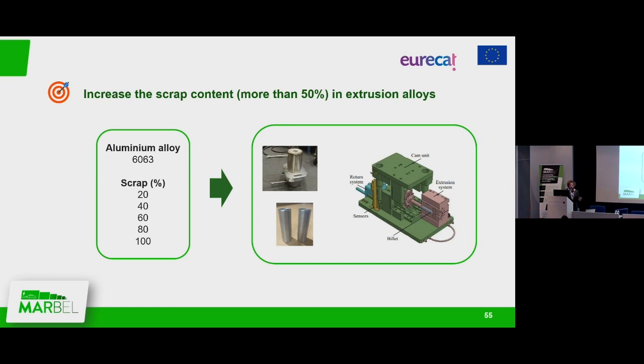Our scope was to increase the scrap content to more than 50% in extrusion alloys. As Elias told before, we used 6063 aluminum alloy, and we included 20, 40, 60, 80 up to 100% of scrap. The billets that we obtained are very little compared with Elias's results. This tooling was designed with the help of Asash, and we designed this special extrusion device.